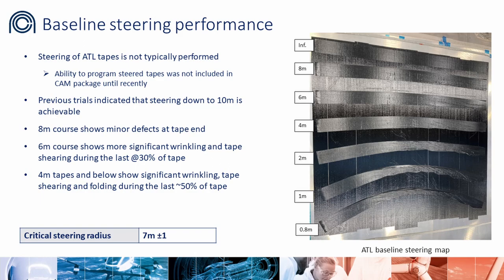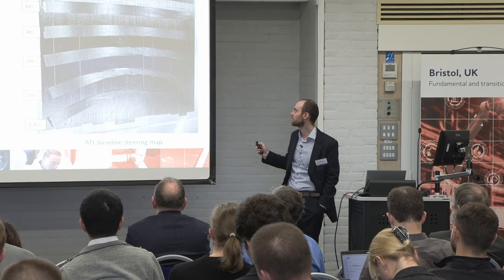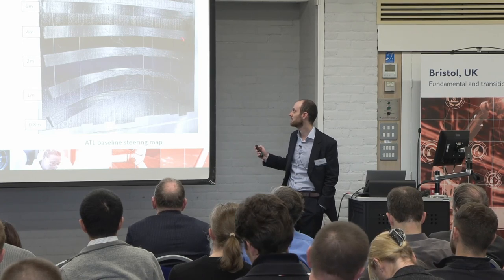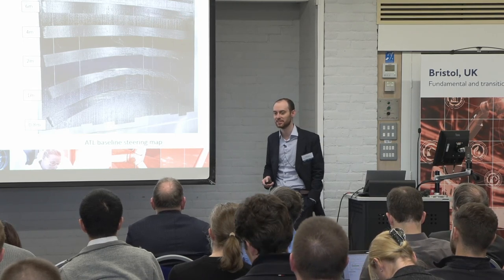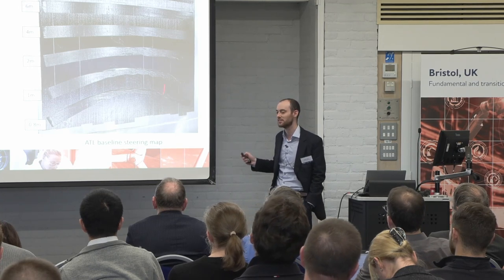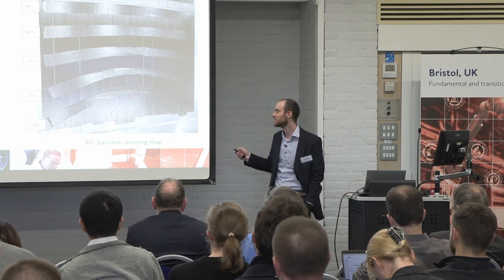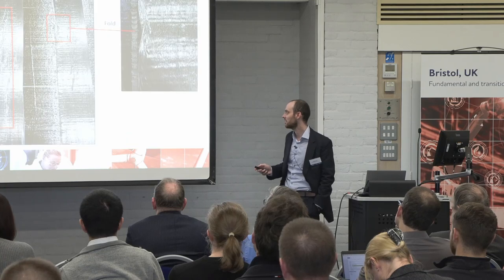As you can probably tell from the picture, this process is very good at laying straight paths at quite a high rate, but as soon as you go below an 8-meter radius, the quality becomes, even visually, unacceptable. You've got a lot of wrinkling in the final third here, and anything below that, at 6 meters, is a miracle it even came out of the machine. This is really bad quality. But there's a reason we did all this, and I'm going to show you in the next two slides why.